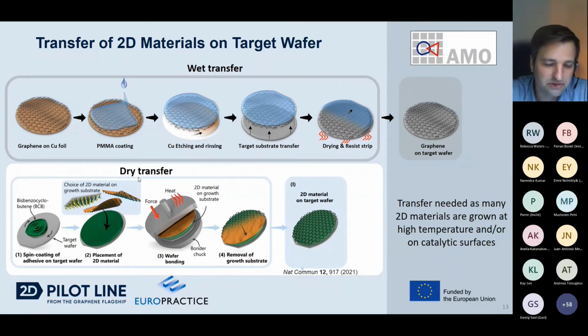The other approach, the so-called dry transfer, also starts from your material on a different substrate, but in order to transfer it to the target substrate, it uses force and heat to bring the 2D material onto the target substrate. This can also be done with an additional adhesive layer in order to bring the forces to the substrate to mechanically remove the growth substrate. And then you end up with the graphene layer on the target substrate. A so-called semi-dry transfer would be if you remove the copper surface, in this case also with a wet etching solution, then you speak of a semi-dry method.